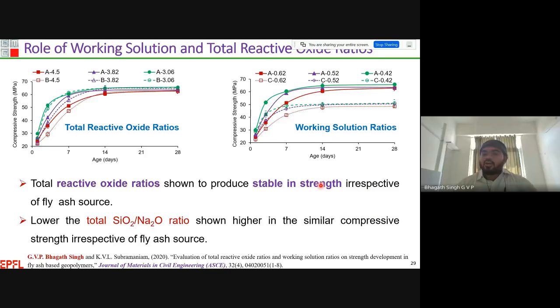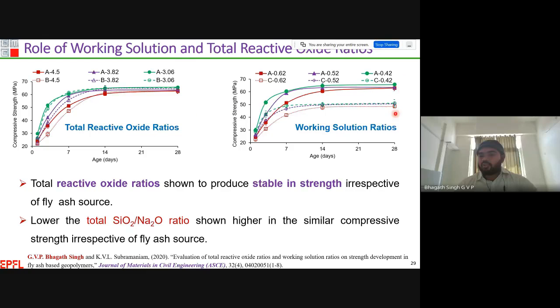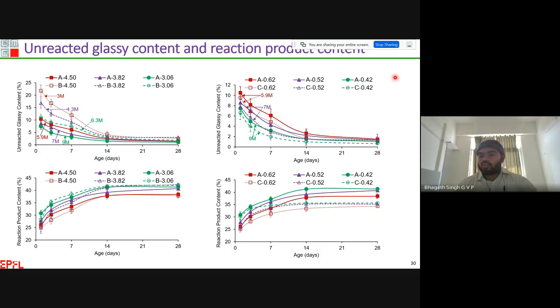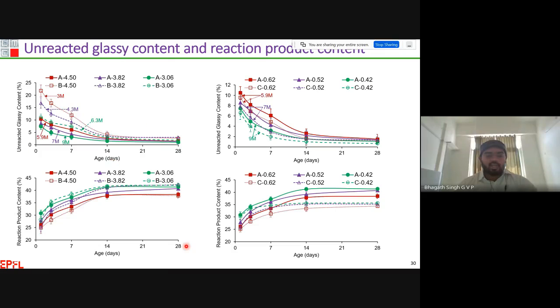Then I have tried different ratios instead of 3.06; I have tried 3.82 as well as 4.5. At any particular time, both fly ash sources show more or less similar compressive strength in the case of total reactive oxide ratios. But in the case of working solution ratios, you can see a significant difference from one source to another source. Then I tried to understand how the dissolution mechanism as well as product formation takes place in these fly ashes.